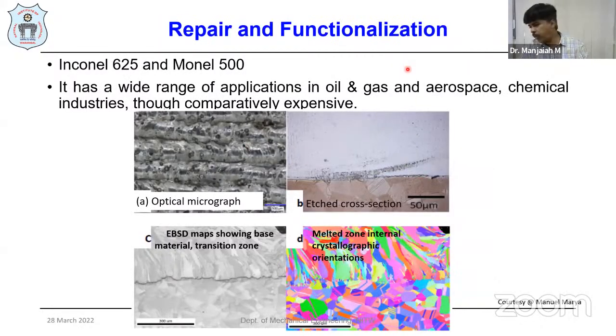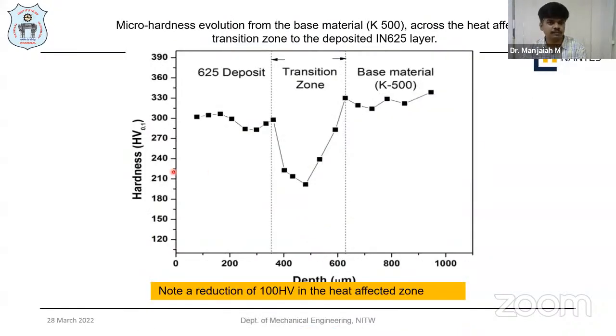And we have used it for some repairing applications, like some Inconel with Monel materials. Because of the wider application in oil and gas industries and aerospace industries, we made a comparative study with additional layers for the repairing applications, to see what the bonded structures between the substrate and the added layers will be. You can see how the grain orientation from the base material to the transition zone was analyzed with EBSD analysis. And the microhardness evaluation was done from the base material to the transition zone, to see how the heat affected zone is affecting the deposited Inconel materials.